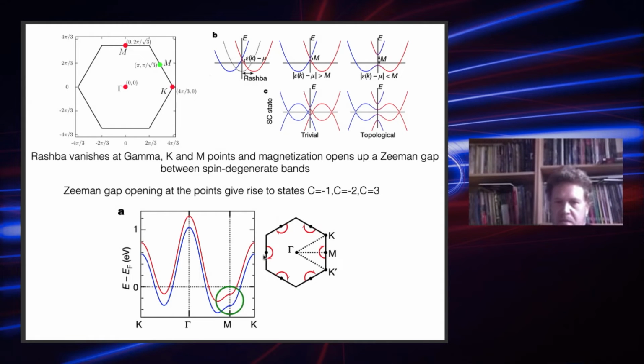And near the M point, in all of these high symmetry points, K and M point, there is a Berry monopole sitting there. Due to the counting of the full Berry flux, we can see that the possible Chern numbers of these gap openings from the high symmetry points are -1, -2, and 3. And in this interesting topological regime, the tentative Chern number of this system would be 3, just due to the crystalline symmetry.